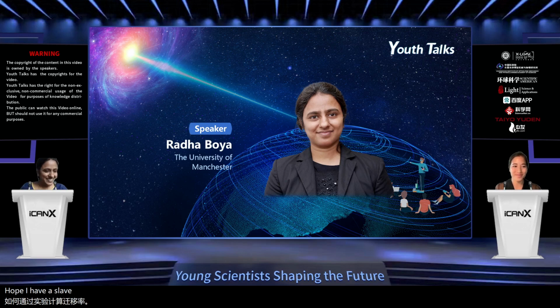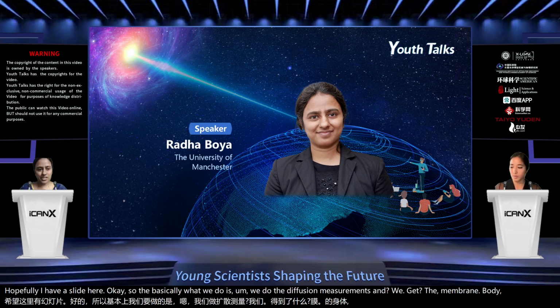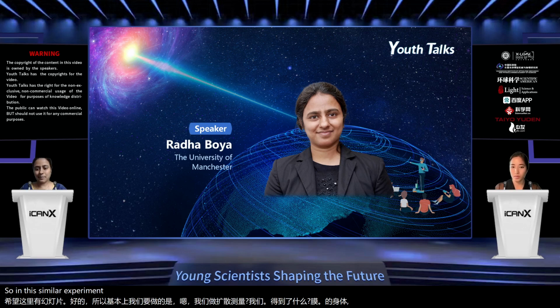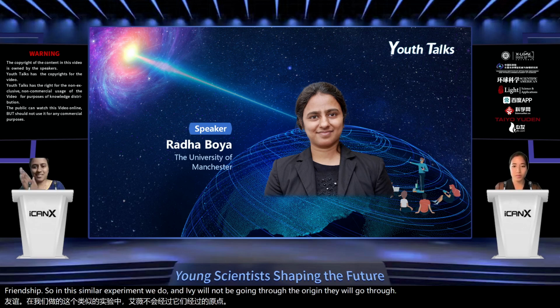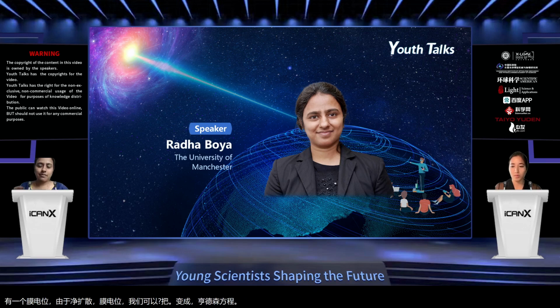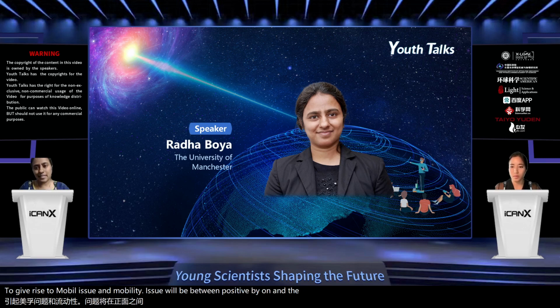Okay. So basically what we do is we do the diffusion measurements and we get the membrane potential. In this similar experiment, the IVs will not be going through the origin, because there is a membrane potential because of the net diffusion. That membrane potential we can put into the Henderson equation to give rise to the mobility ratio, between the positive ion and the negative ion. And from that, in conjunction with the conductivity, we can calculate the individual ion mobility.